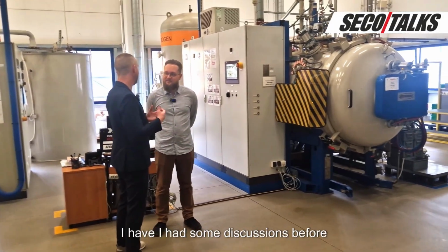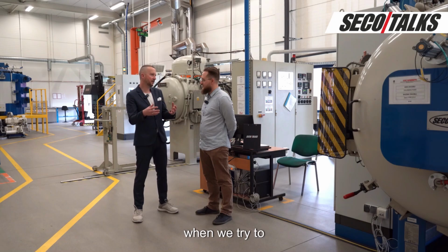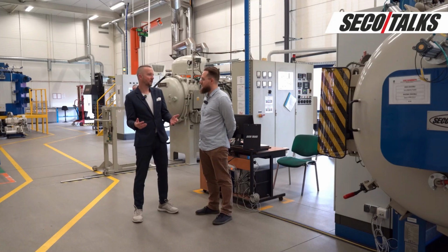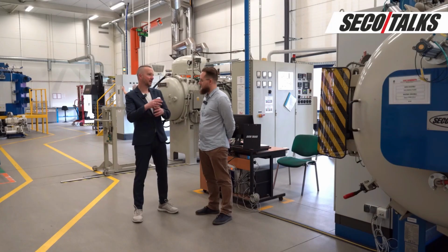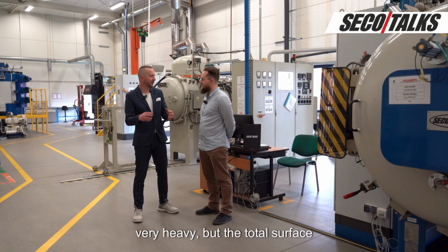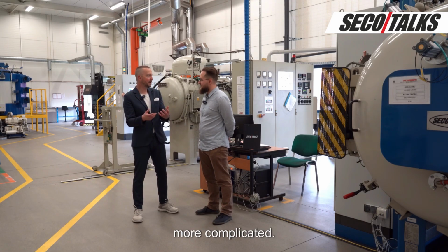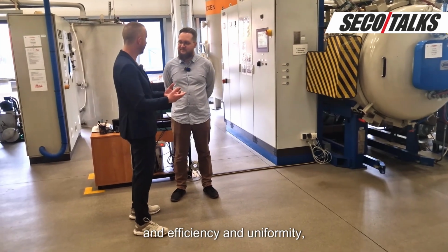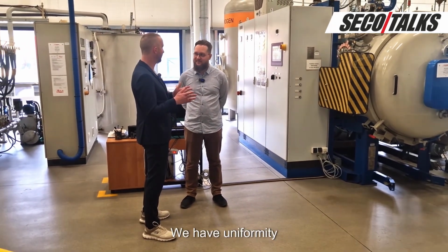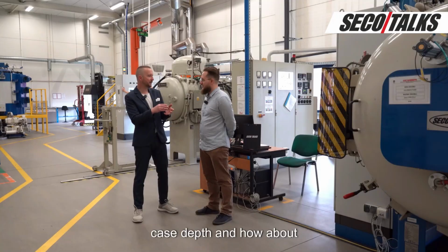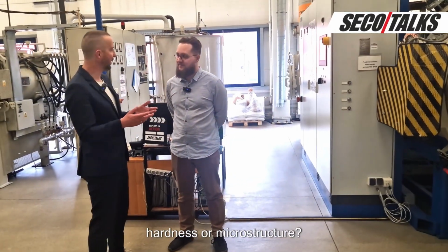This is a good point. I had some discussions before when we tried to dedicate the product or technology for one single component, a large gear with very big weight, like 5 tons or more, but the total surface was even reduced by some stop-off paste. In your case, 4,000 components, maybe the weight is not very heavy, but the total surface makes this process more complicated in terms of efficiency and uniformity. Yes, exactly. We have uniformity related to the case depth, and how about uniformity related to other points like surface hardness or microstructure?